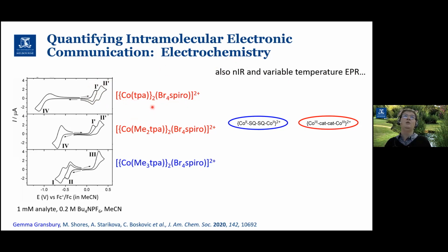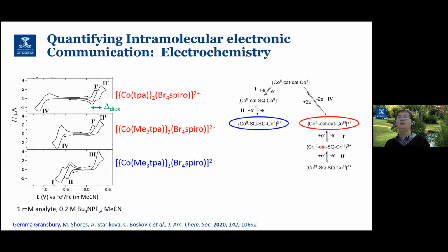So in these two red complexes here, the complex is in the cobalt-3 catechol cobalt-3 form at room temperature in acetonitrile. So in that case, those processes correspond to sequential one-electron oxidations of the spiro ligand, whereas the trimethyl TPA of the bromospiro is in the cobalt-2 semiquinone cobalt-2 form. So those two processes there correspond to sequential one-electron reductions. In any case, the potential separation between those two processes correlates with the electronic communication across that bis-dioxolene ligand. So whether it's a spiro bis-dioxolene or any bis-dioxolene.